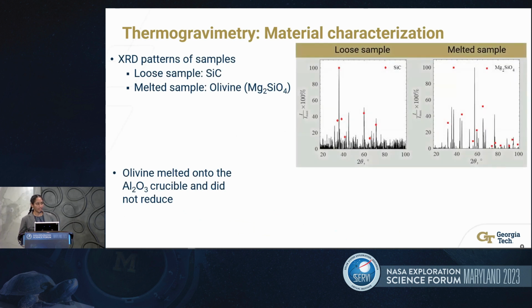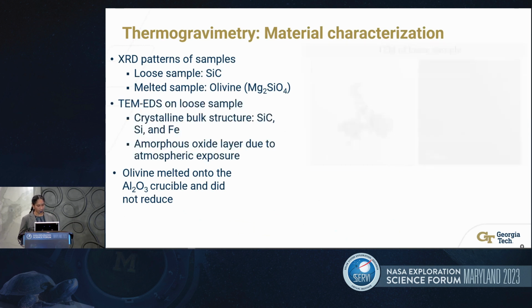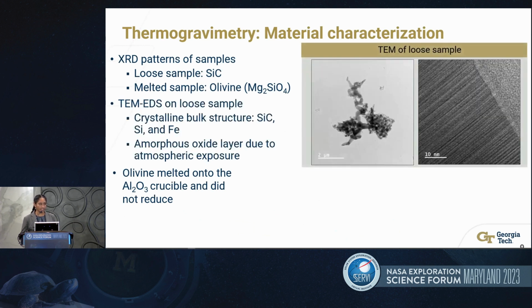The loose sample and the melted sample were then studied using XRD. Silicon carbide was detected in the loose sample and olivine was detected in the melted sample. This means that the olivine mineral, specifically Mg2SiO4, simply melted on the crucible and did not react. The loose sample was then studied using TEM and EDS.